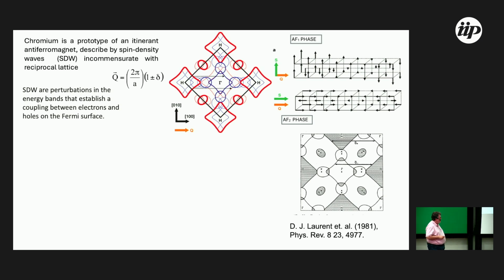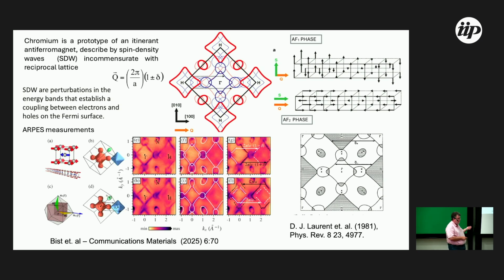Laurent in 1981 calculated the Fermi surface of chromium and observed the difference of the holes and the electrons. And it is very interesting, this paper recently published in April 2025, direct observation of the Fermi surface by ARPES measurements. And observe exactly the behavior 2π/a (1 minus delta), 2π/a (1 plus delta). It's a recent paper, published on 25 April, one month ago. Observe exactly this characteristic of chromium.